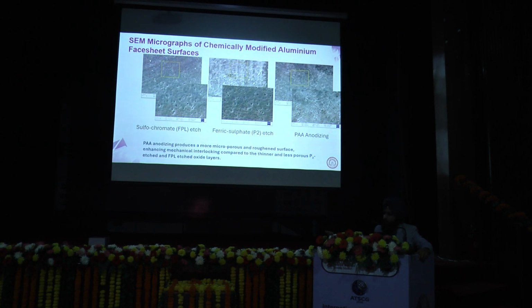These are some micrographs you can see. The first one here is the sulfochromate etch, in the center one you can see the ferric sulfate P2 etch, and the last one is anodized samples. In the anodized samples you can clearly see the deep micro pits and pores enhancing the interlocking. I will be explaining this phenomenon later. The oxide layer has more deep micro pits in anodized samples as compared to the first two etched samples.